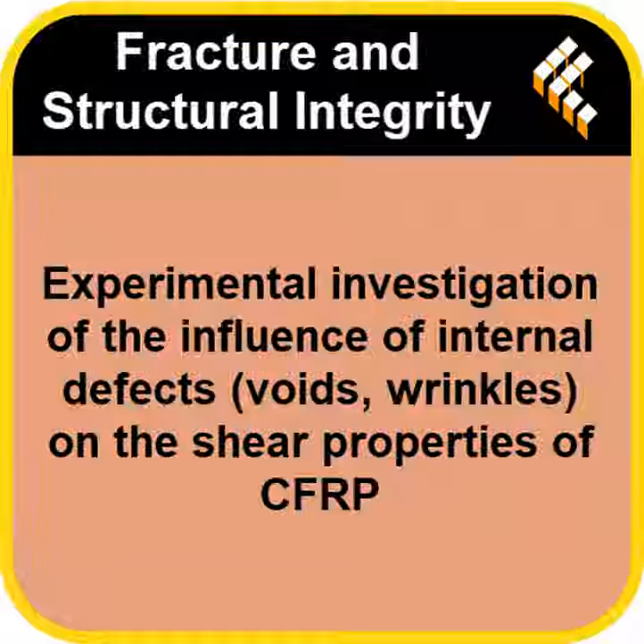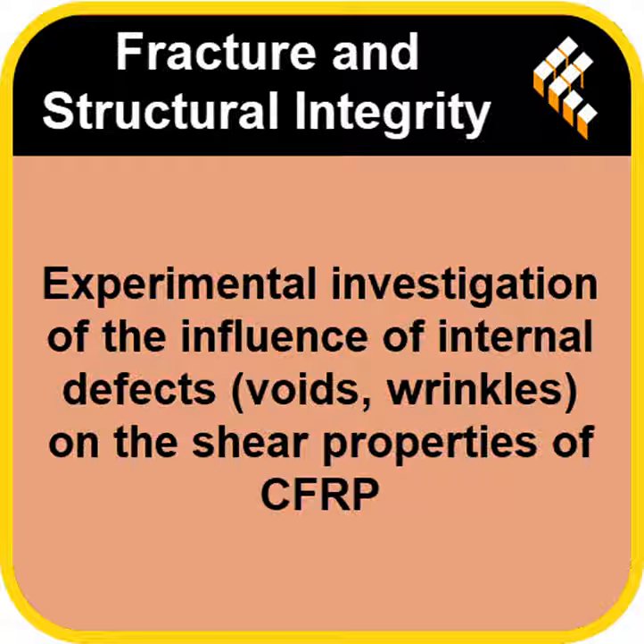And for wrinkles at around 10% concentration: also a minimal strength drop, maybe 3%, but a noticeable increase in stiffness, likely due to the thickness increase caused by the wrinkle itself. Right. So both are fairly benign in terms of ultimate shear strength at these levels, but they affect the elastic properties, the stiffness, very differently. Precisely.